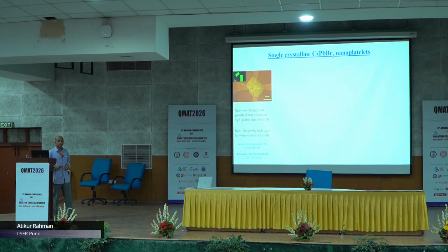But the problem with this material is that it is water soluble. So the moment you try to do photolithography especially, it gets dissolved. So we figured out a modified photolithography technique to make electrical devices on it, which you'll find in this manuscript.